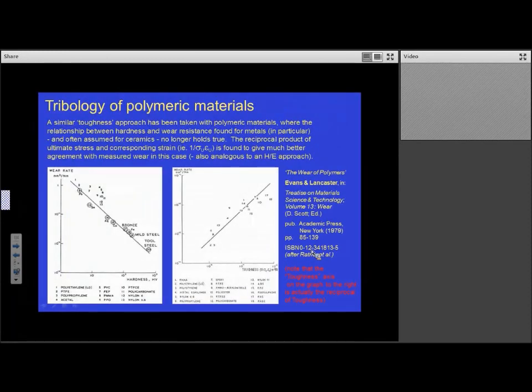There's also an argument around toughness for polymers. Another guru of the subject, John Lancaster, did a lot of studies, and he was one of the leading lights, sadly passed away in 2014. John looked at the wear of polymers and found that those giving the lowest wear rate were the ones with the highest toughness. This is actually the reciprocal of toughness here. So the ones with the highest toughness are the ones here giving the lowest wear rate. So again, there's a toughness argument even for polymers, which holds true. Again, this sigma u, epsilon u comes into this consideration.